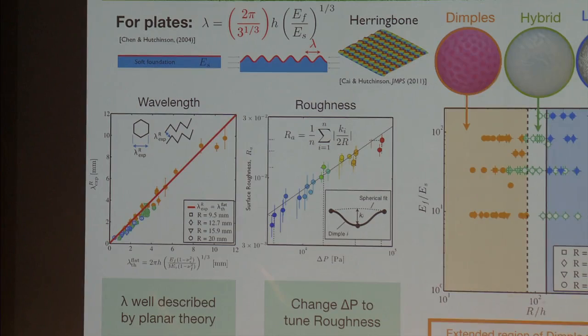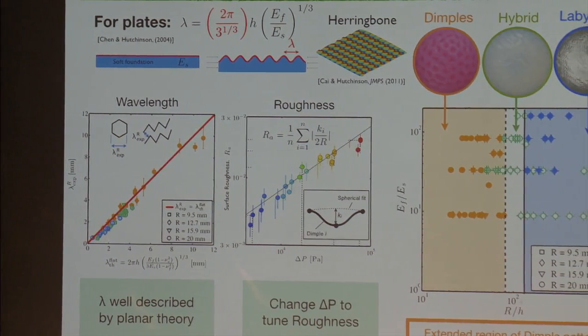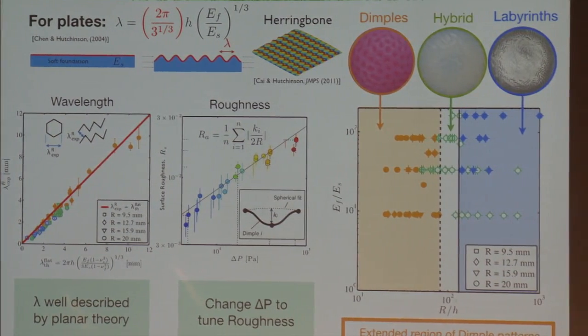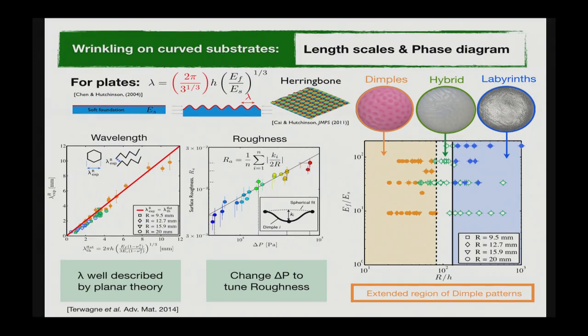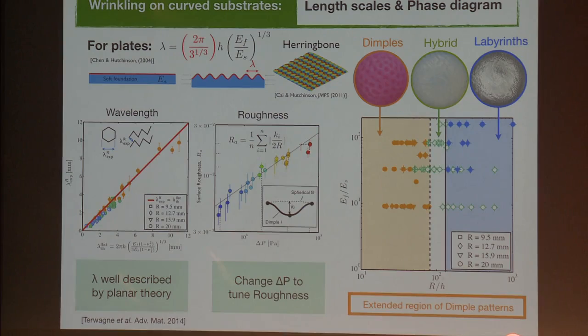Now, the fact that we're seeing these crystalline dimple patterns, which would not have been very easy to see at all, other than a very small region of parameter space for flat systems, here now they're very prevalent. So if I plot a phase diagram with ratios of stiffness between the film and the core as a function of the ratio between the radius of the sample and the thickness of the shell, there's actually an extended region here over which we see dimples. So curvature is modifying the pattern that is getting selected.